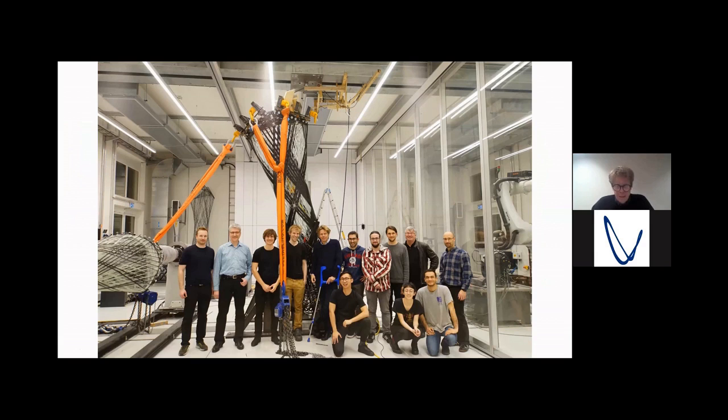I find this pretty interesting because large scale additive manufacturing processes allow for a very differentiated load-adapted fiber layout. But at the same time, you are thrown back to kind of pre-industrial engineering by trial and error because these components are defined, the performance of the components is defined by so many parameters that cannot be reliably simulated.